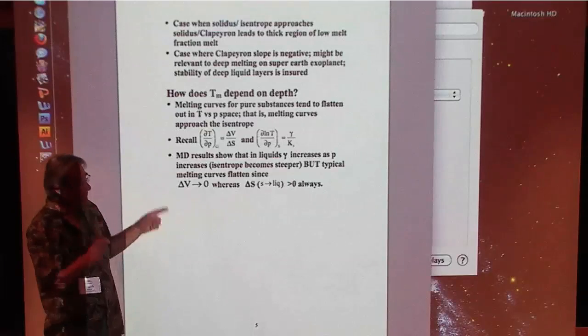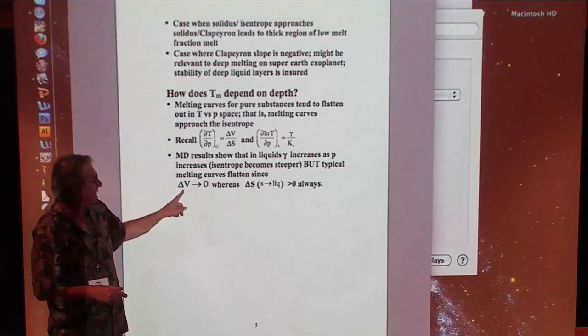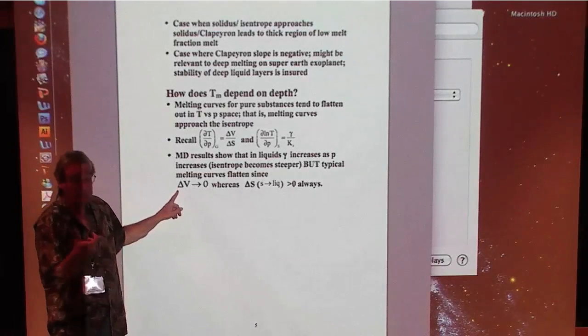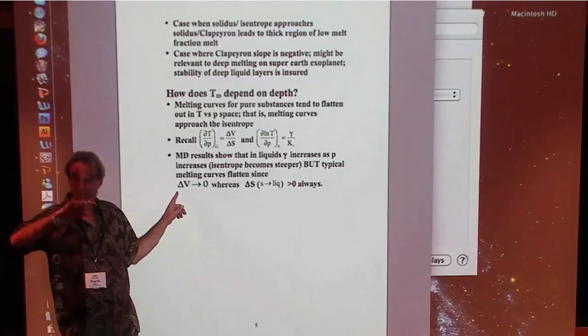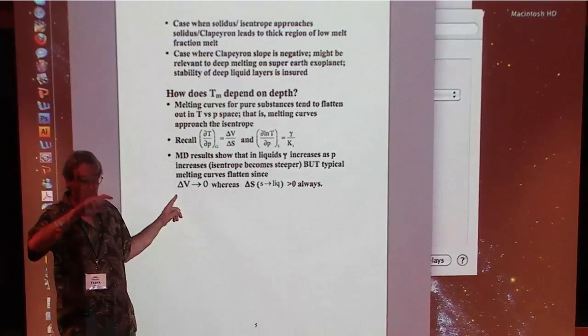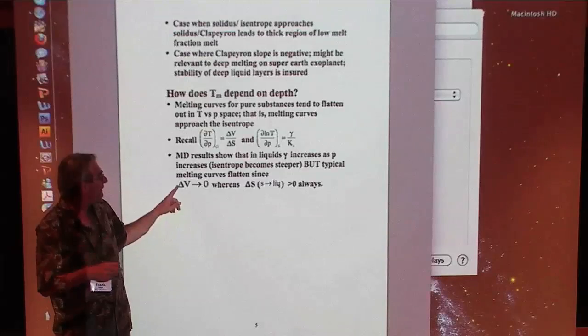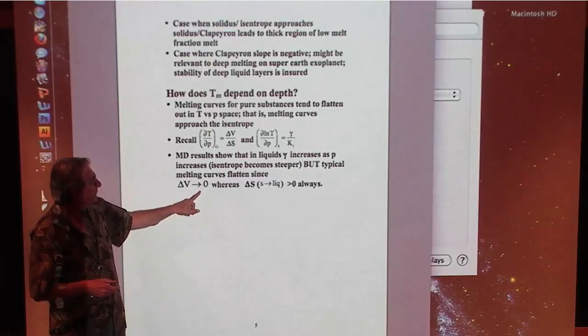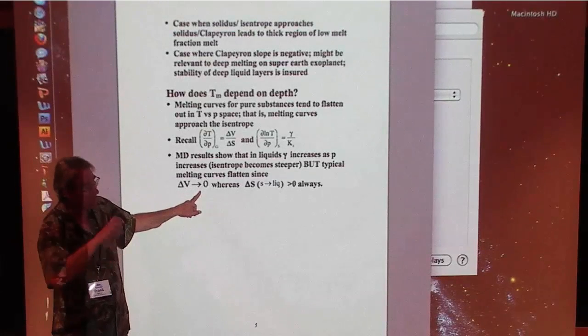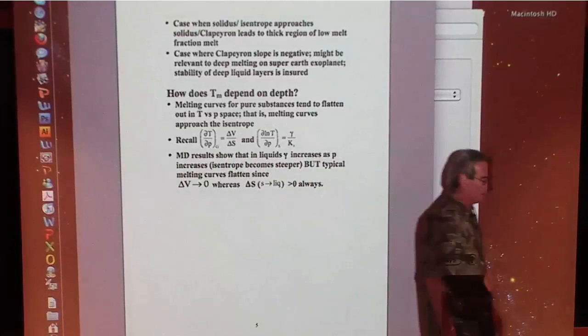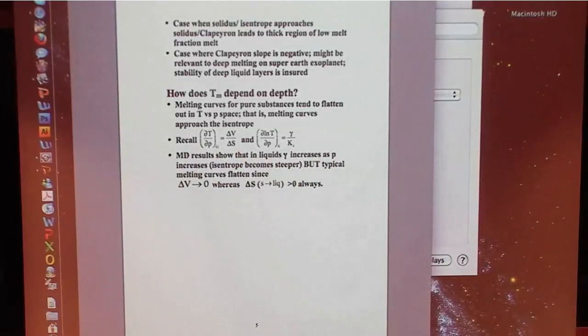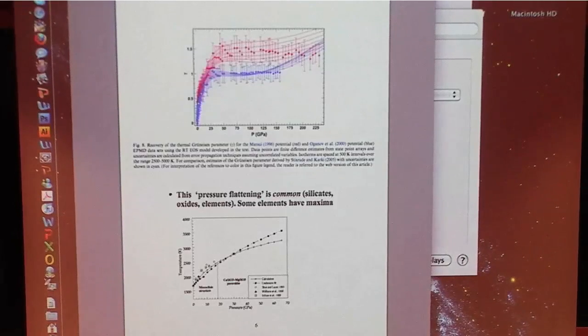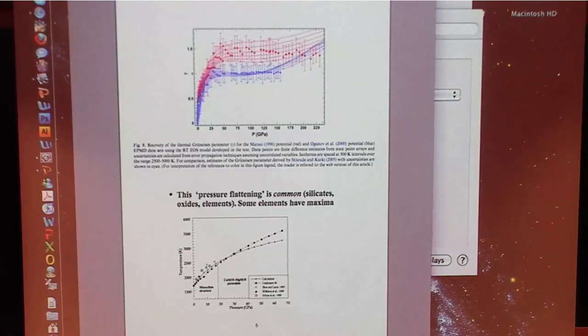Okay, but the really cool thing is that delta V here, which is basically saying, is the liquid denser than its parent solid or less dense, can go to zero and actually can be negative, right? I mean, ice and water. So the top one is just to show you that the Grüneisen parameter does depend on pressure, especially up to about 30 or 40 GPa.